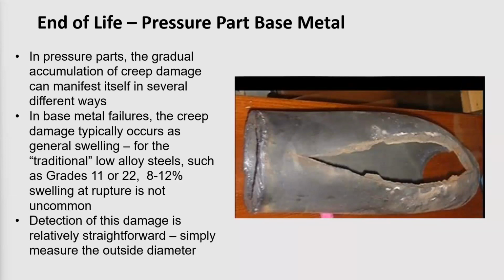In terms of end of life, if you're dealing just with regular base materials, so the sections of the piping between two girth welds, for example, if you were to encounter a situation in which that piping would reach its end of life, the visible manifestation of that would be quite obvious, in that under normal circumstances, these materials have very good rupture ductility, and so the evidence of distress is going to be seen as swelling of the piping. And if the damage progresses to the point of failure, what you'll see is, as is shown in this picture, almost like a fish mouth type failure in the part once it's swelled to a very significant extent, oftentimes in excess of 10 to 12% rupture strain.